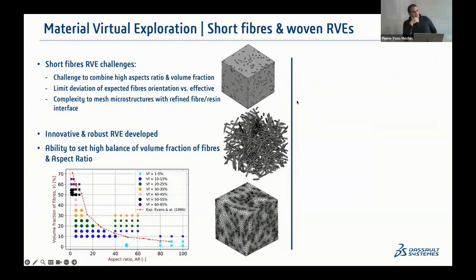I've been chasing a lot for composite material, long fiber composite material, but we worked a lot this past year on short fiber RVE models, with the challenge of having high aspect ratio and high volume fraction RVEs. So what we have here is how we can generate microstructures which combine high volume fraction and high aspect ratio. This is work underway at the moment.